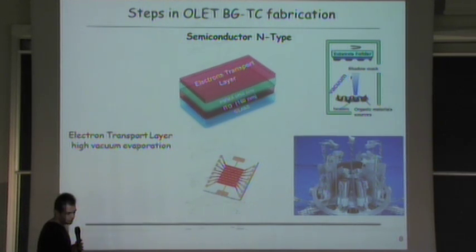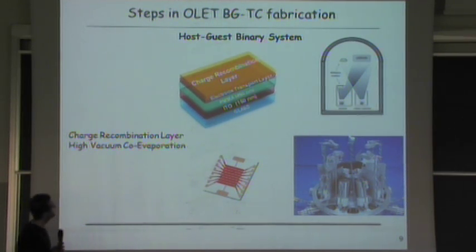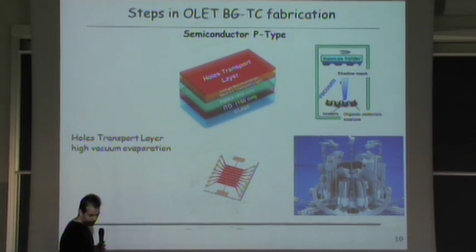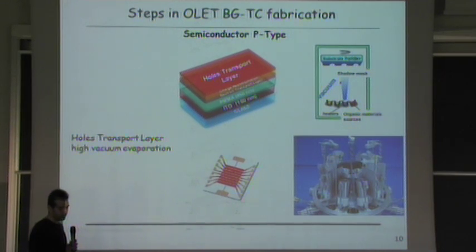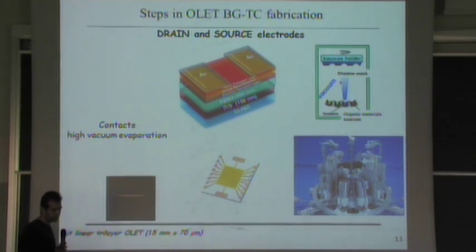I sublimate the electron transport layer in high vacuum evaporation using only one organic material source. This is the host-guest binary system able to create the charge recombination and so the light emission. I use here 2 different crucibles because we create a binary system, so I have 2 different deposition rates for 2 materials in practice. Then the holes transport layer, and finally the drain and source electrodes.